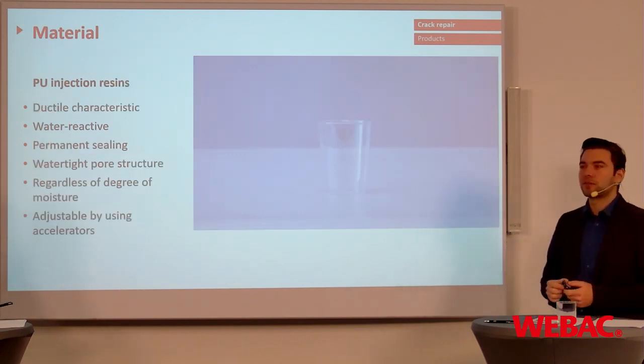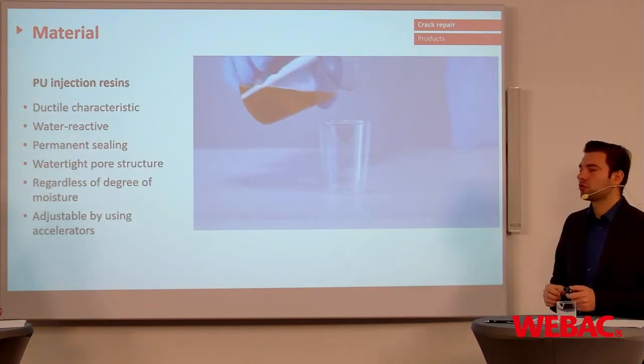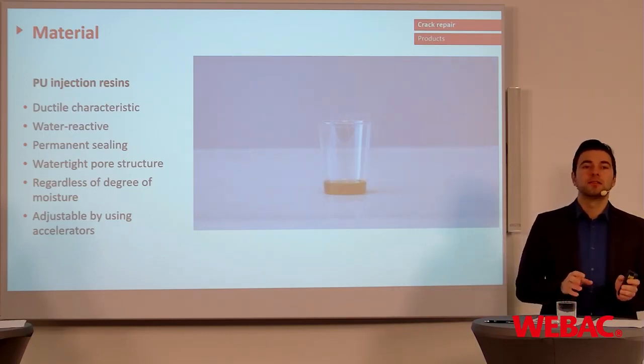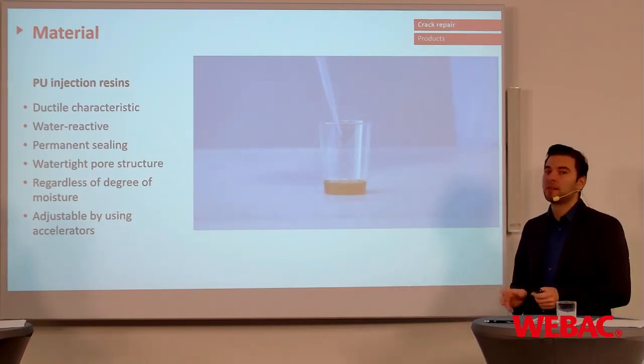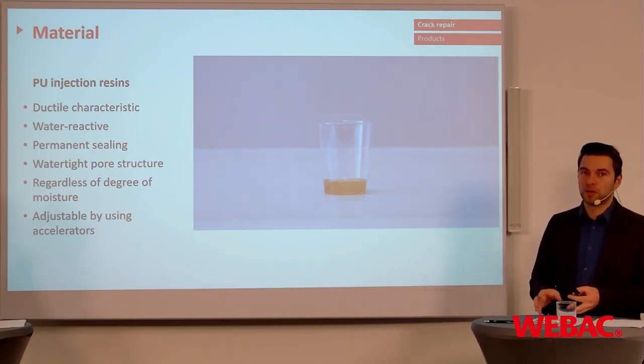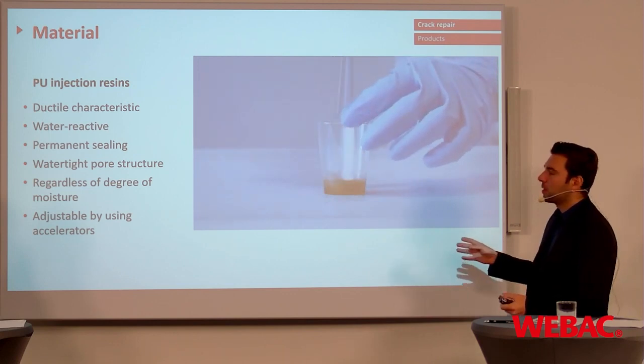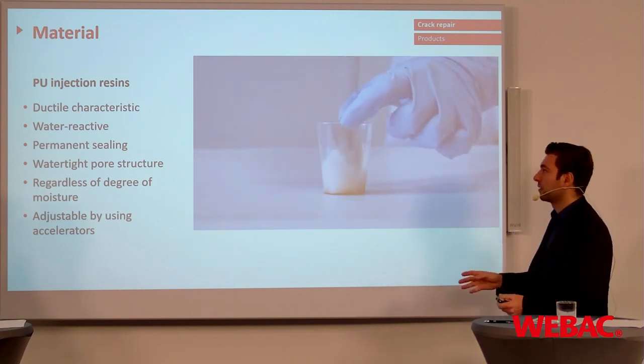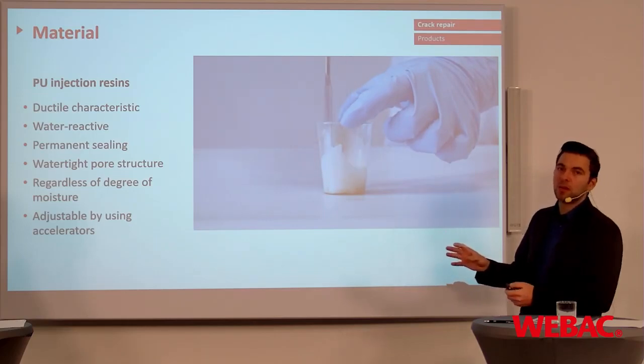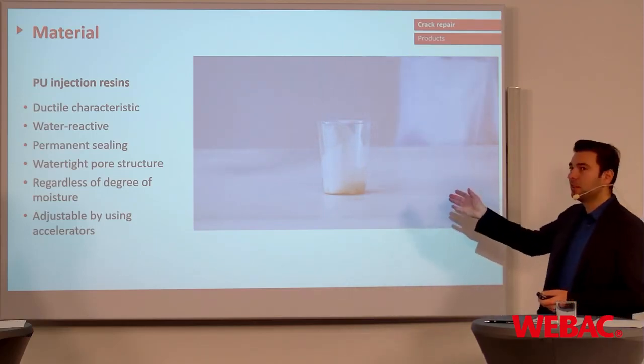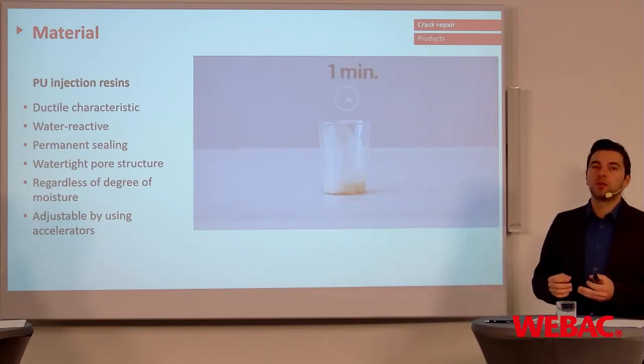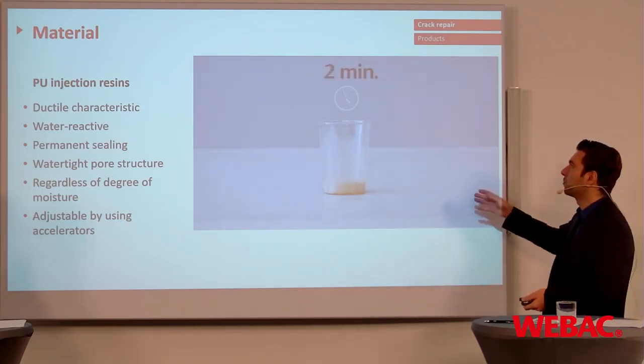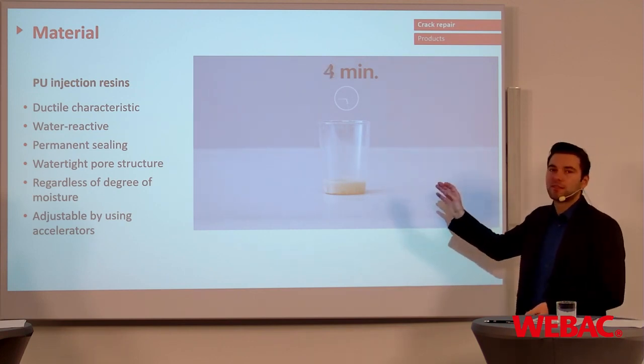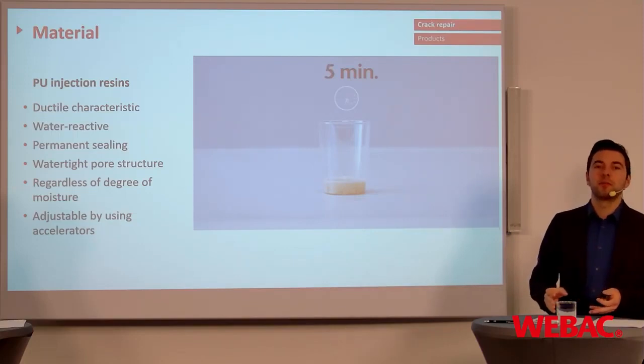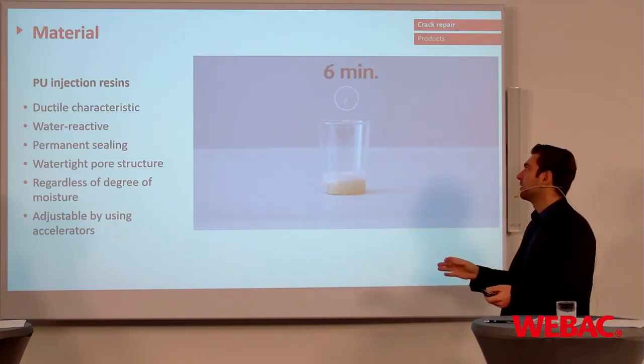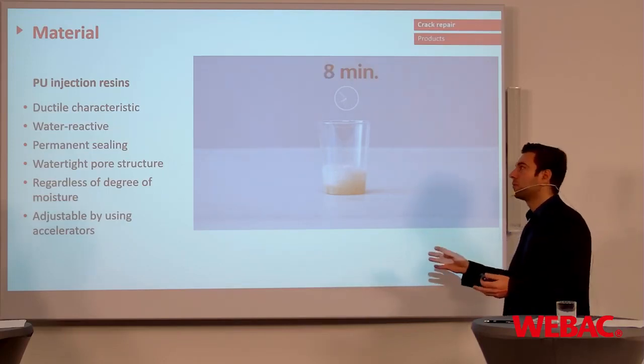Now, coming to the next injection material, we are talking about the PU injection resins. They are designed for the ductile filling of cracks, and they can be used in dry, damp, and wet cracks. So they are very flexible. Also water reactive, so if they come in contact with water, like you can see in the video, this material also starts to foam. But as you can see, we just put it on a time lapse. It's not seconds, we are talking about a certain time of minutes. Depending on the material, it can be between 10 to 30, 40 minutes.